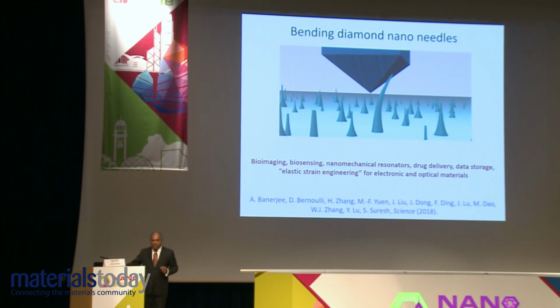So we decided to try this by using some of the latest tools that have become available in the last 10, 15 years or so. We take these diamond needles on a substrate inside an SEM, where we can use a diamond tip in a nano indenter to either push it down or come sideways and bend it and see how much it bends. And we can try to impose different amounts of controlled elastic deformation. Of course, there is anisotropy.